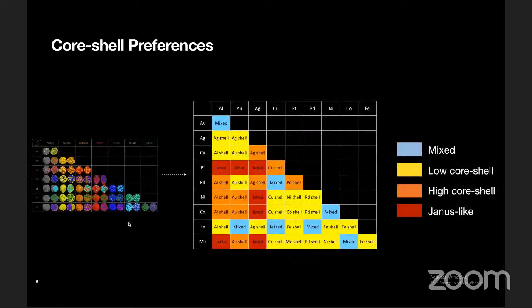So what we did is that we converted the MD results into a table that shows the equilibrium structure of each combination and which metal segregates on the surface or forms the shell. Now, if we look at aluminum here, when it is combined with other materials, it tends to form the shell or the surface. On the other hand, platinum tends to occupy the core when it is mixed with other metals.